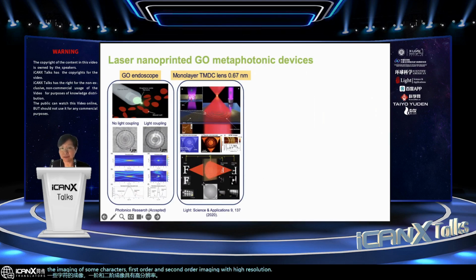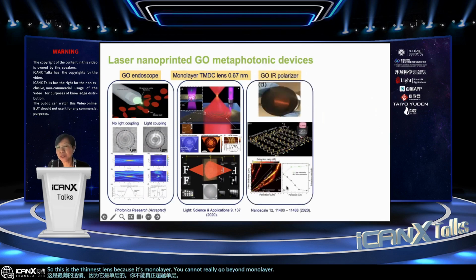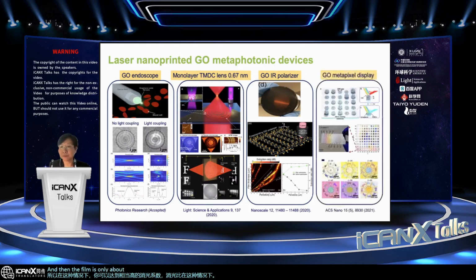So this is the thinnest lens, because it's monolayer. You cannot really go beyond monolayer. So in the meantime, there are also other optical elements you can fabricate. So for example, the IR polarizer, because graphene oxide has really nice IR property, very low absorption and high refractive index. So using the simple grating structure, you're able to make an IR polarizer. So otherwise, polarizer is very difficult and very expensive to make. So in this case, you can achieve quite high extinction ratio in this case. And then the film is only about 2 micrometer.